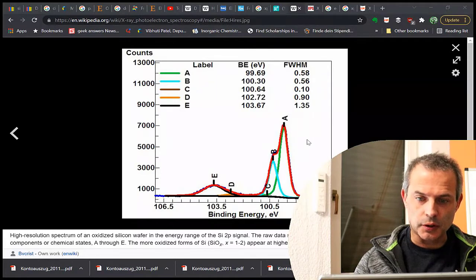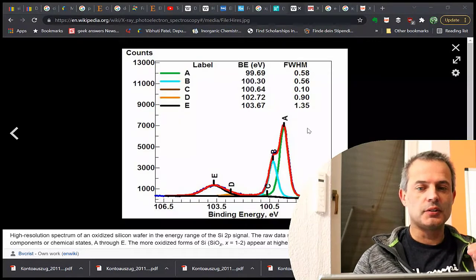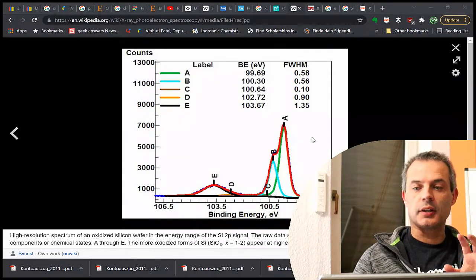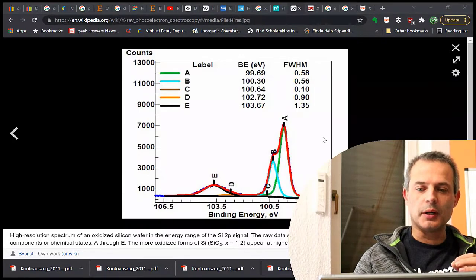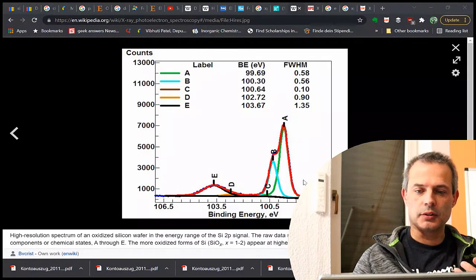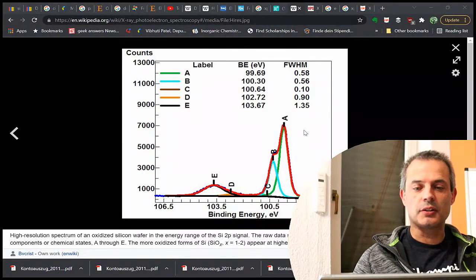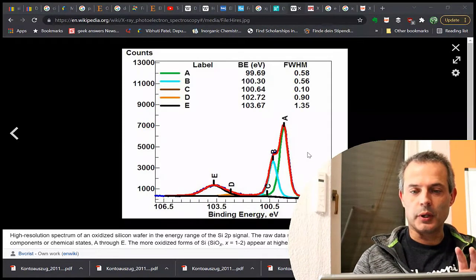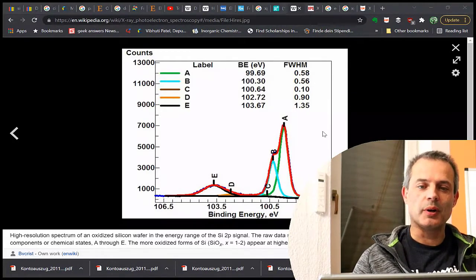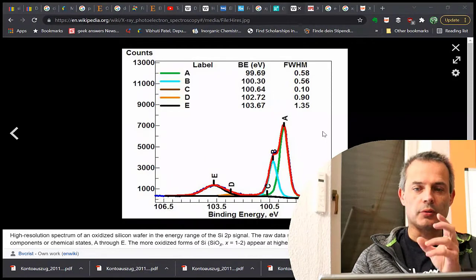It's of oxygen, I think, and it's, oh, hang on, I'll check. No, it's of silicon. So this is the zoomed in version of silicon, and we can see that they have done some fitting. These are curves that are fit to the actual measurement to be able to extract how much of a percentage of the silicon in this case is in different oxidation states. So we've got the various oxidation states of silicon, and we can see them in the shift of the peak for silicon, as long as we can be sure that we know where one is, because again we have to remember that if the sample charges up, all of the spectrum is then shifted.